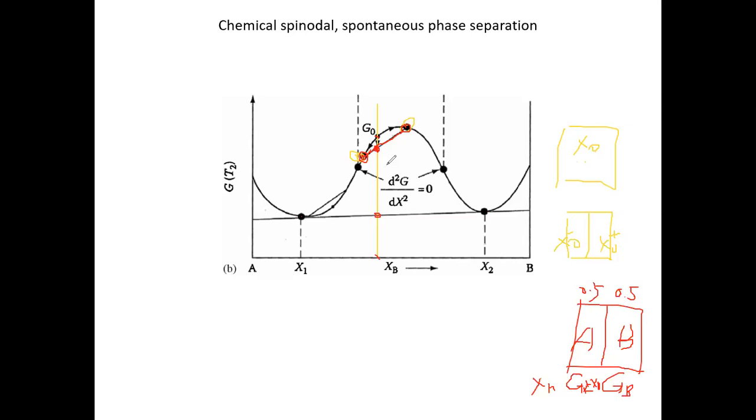So you see that, okay, I start with a small fluctuation, but this small fluctuation does not increase the energy, at least for the particular X naught I choose. It immediately decreases free energy. So there's nothing to stop me from continuing this separation, right? As you can probably see, we start from here and separate by a small amount.